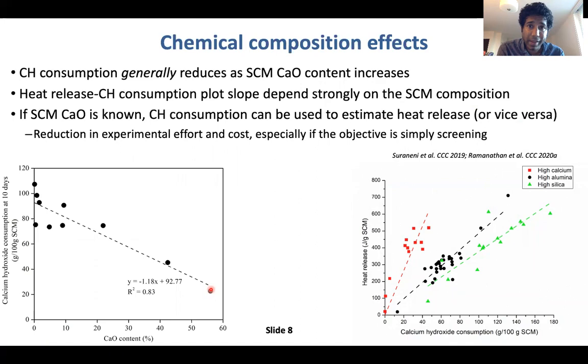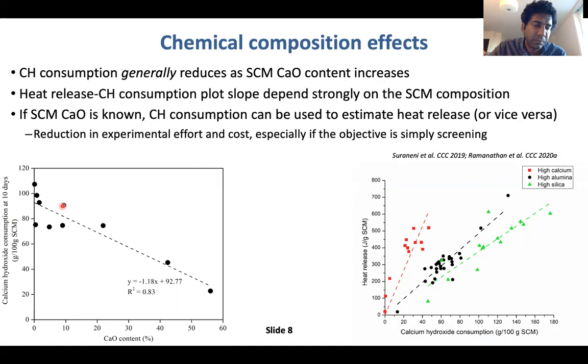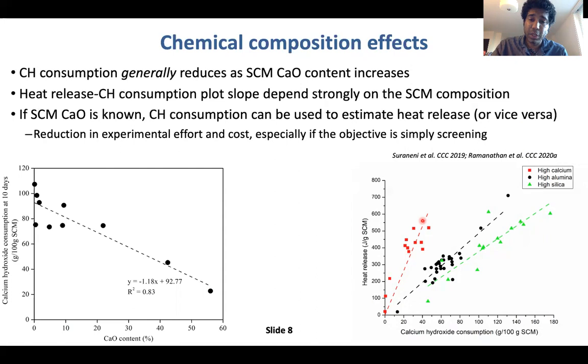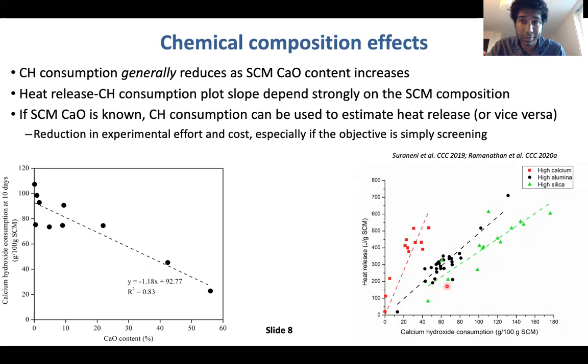We see very strong correlations with chemical composition — here is a correlation with the bulk CaO content. Obviously this is limited in the sense that in reality it's amorphous content that matters, but it's a nice starting point. Perhaps more interestingly, the relationship between heat release and calcium hydroxide consumption actually depends on chemical composition: the slope varies depending on whether the material is high SiO2, high Al2O3, or high CaO. This is something you can exploit — if you know the chemical composition, you only have to measure one parameter and estimate the second from the first.